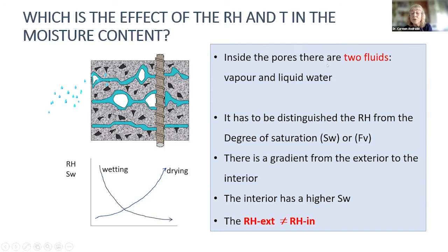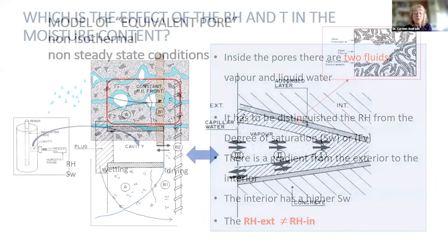Inside the pores, there are 2 fluids. One is the vapor, the water vapor, and the other is the liquid water. And it has to be distinguished, the relative humidity, which is the amount of vapor in the atmosphere, from the degree of saturation or the volumetric fraction. And there is a gradient. In the interior the degree of saturation is higher, and externally and internally they have different relative humidity.